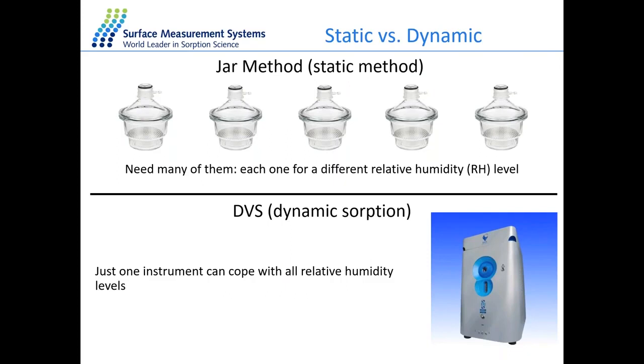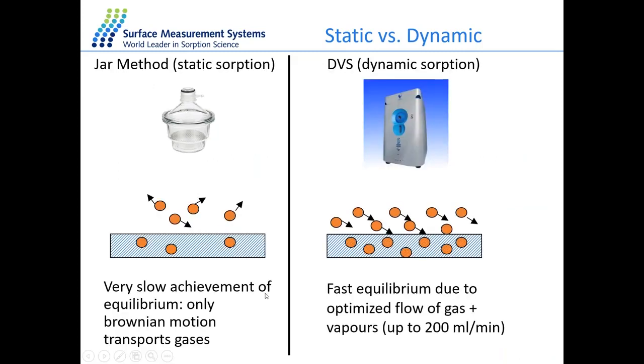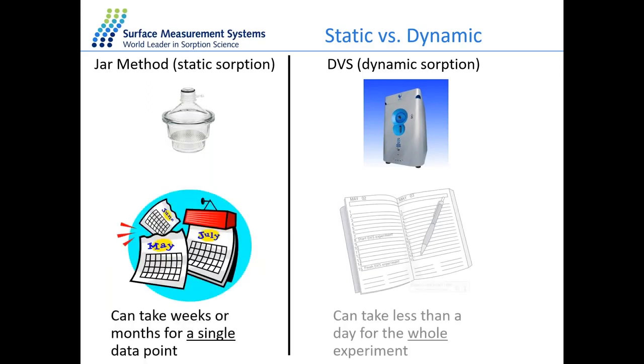So we can actually compare this method to a static method. The static method here is the jar method, and this can be comparable to our dynamic vapor sorption. And for the jar method, we need various different jars for each level of relative humidity. So in the static sorption method, we introduce the probe molecules, but we have very slow achievement of equilibrium. This is because it's only depending on Brownian motion of the molecules being transported. However, in our case, we're looking at fast equilibrium and more optimized flow rates. And in this case, we can actually have more control over the species onto our material. And this fast equilibrium, of course, speeds up the time of your experiment.